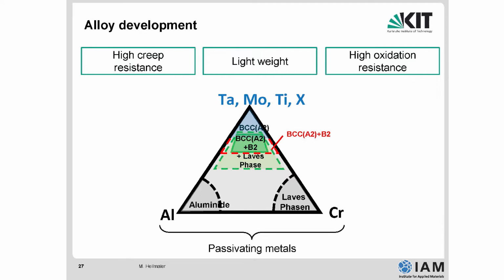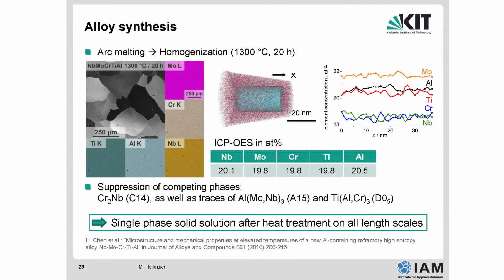And of course, we are aiming for high creep resistance, lightweight, and high oxidation resistance again. For high oxidation resistance, we go for the passivating elements, aluminum and chromium. In this case, we want to form an alumina or chromia scale, which is oxidation protective. And these alloys are for high temperature creep strength. So how do we do it? Again, arc melting, quite simple. Then a homogenization treatment, and then we have to check the chemical homogeneity on various length scales.